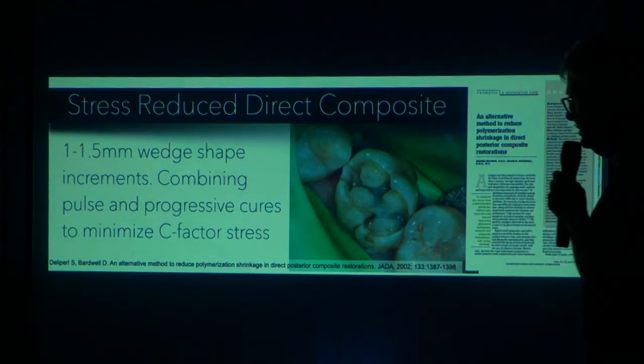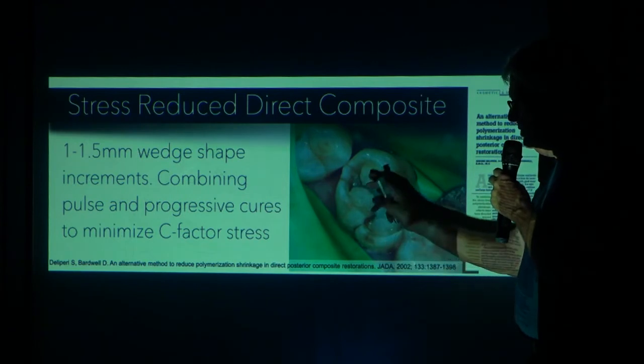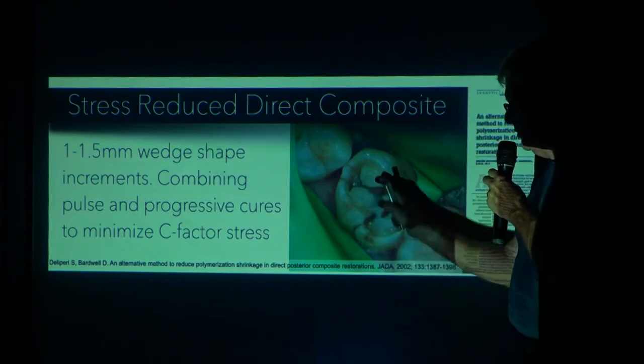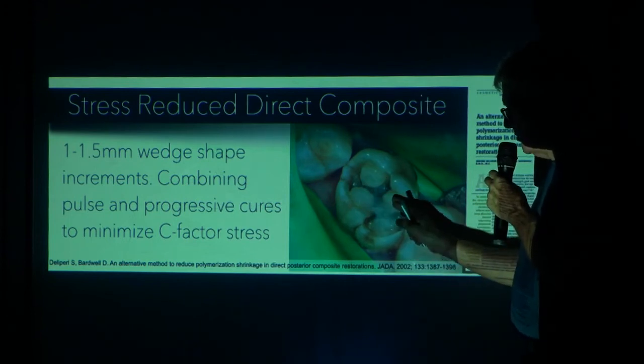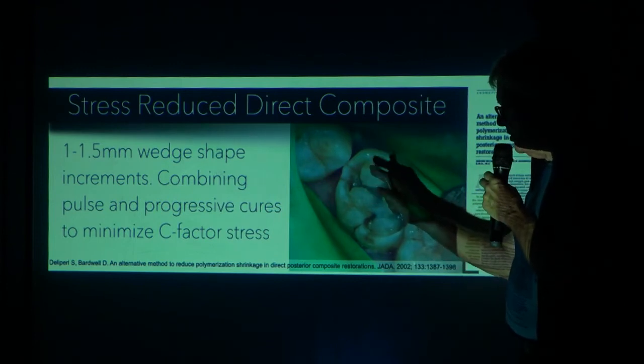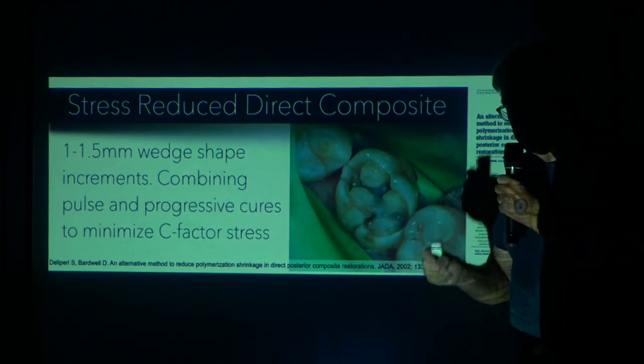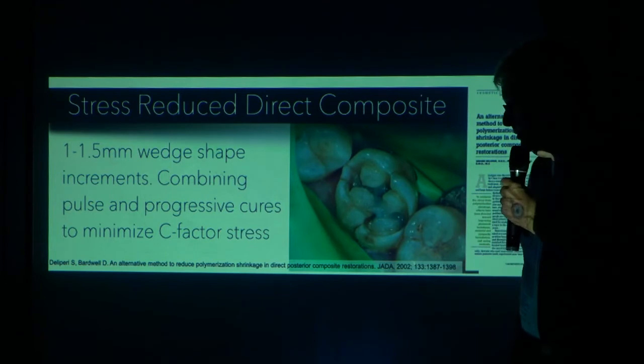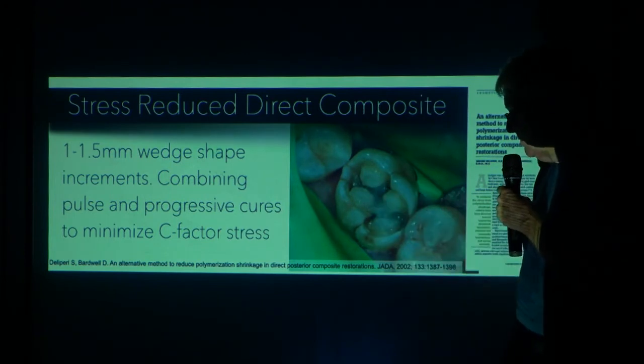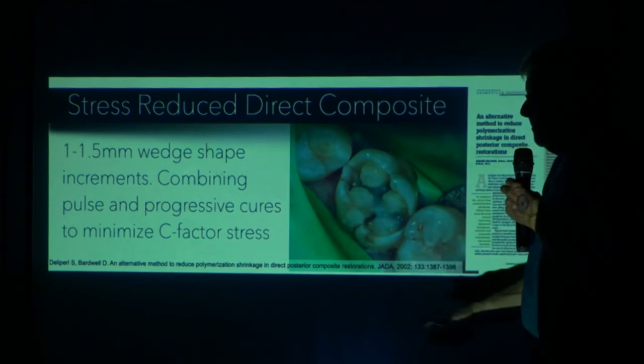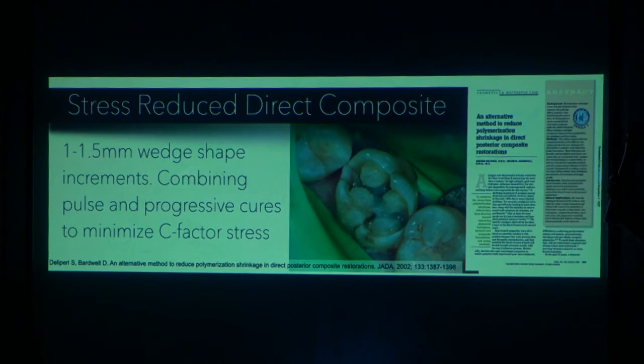And so here's an old case that I did, but we added fiber underneath the stress-reduced small volume increments. If we use 1.5 to 2.0 balls of composite, they're only touching dentin, then when they polymerize, they only move towards dentin. And they're only engaging one part of the hierarchy of bondability, that of deep or intermediate dentin in this situation. We had about 2 millimeters of dentin replacement and 2 millimeters of enamel replacement. But these 1 to 1.5 millimeter wedge-shaped increments combining pulse and progressive cures to minimize C-factor, this is called the stress-reduced direct composite technique. We named that in 2009. In 2002, it didn't have a name. But the paper that we published in JADA still is a very important paper to understand this technique.